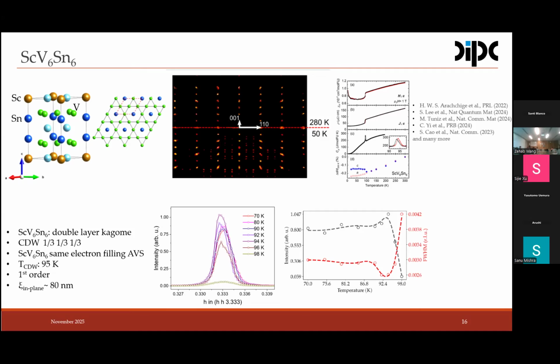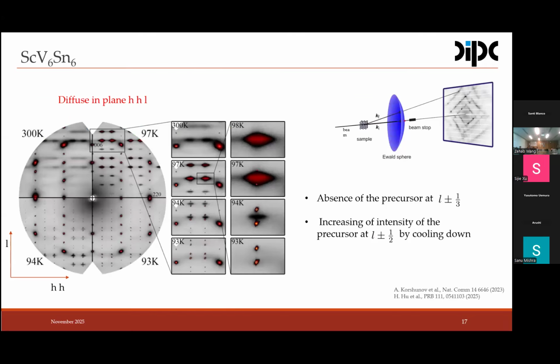The first thing we notice is that the charge order is first order in character. It has a small hysteresis, but as we measure in resonant diffraction, it's actually very sharp, around 95, 98 Kelvin. So we take the sample and put it in the diffuse scattering, and already at 300 Kelvin, we see some diffuse signal in the HH plane, like streaks of intensity at half integer values of L. Once we cool down, this diffuse scattering starts to increase until we reach the transition temperature of 95 Kelvin, and then the diffuse signal is suppressed, and the superlattice peak at L 1/3 appears.